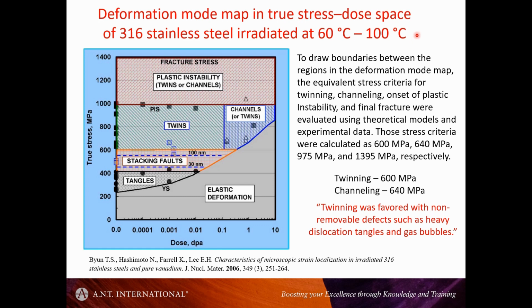I mentioned that in the austenitic stainless, in the Inconel X750, at this temperature, actually we didn't get any damage, but it seems that in 316 stainless steel you do. So I'm not sure why we get that difference, but it's still diminished relative to the 300 degrees C. So even though we have a lower damage density at these temperatures, you can map out what type of deformation mechanisms apply at different regimes as a function of dose and as a function of the stress.